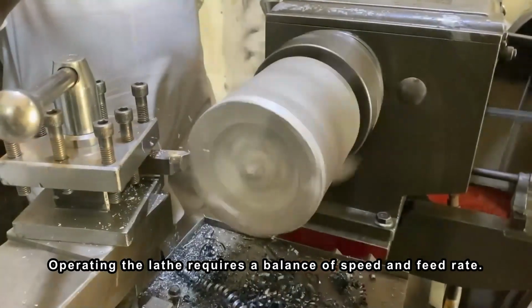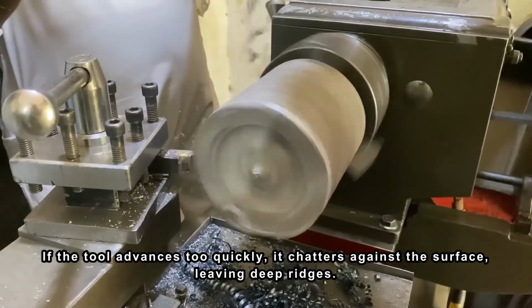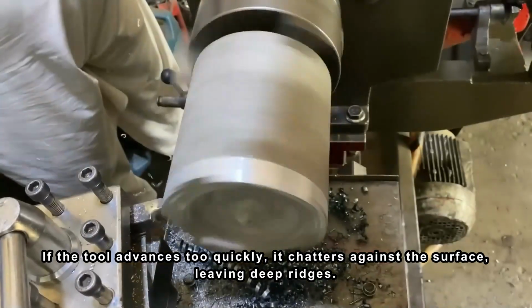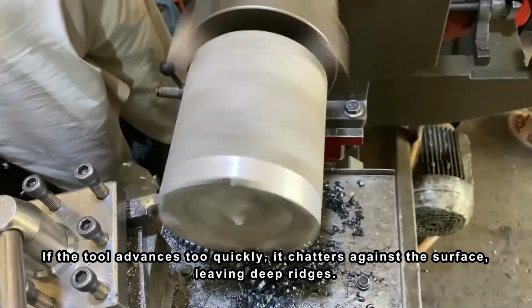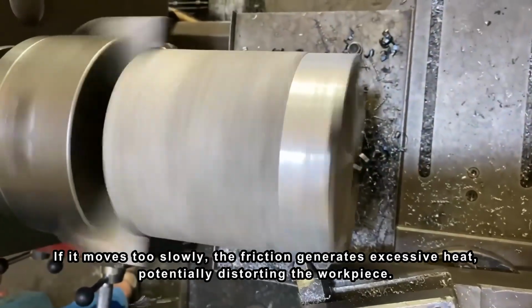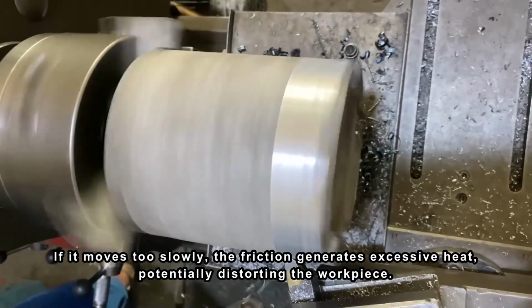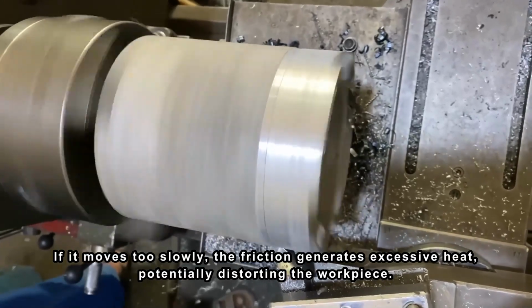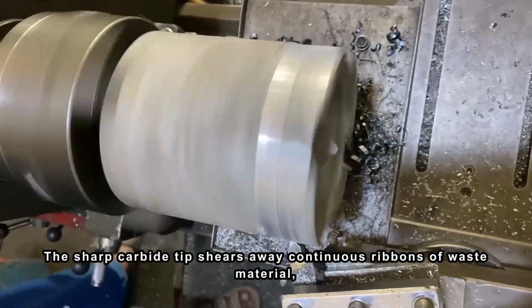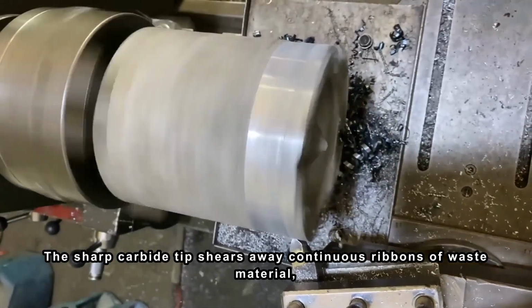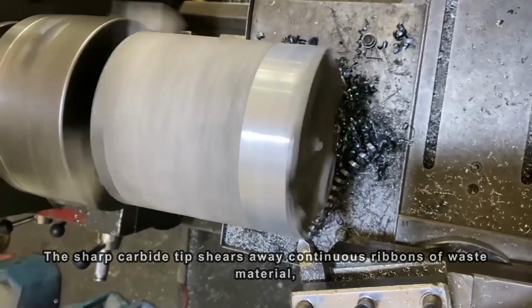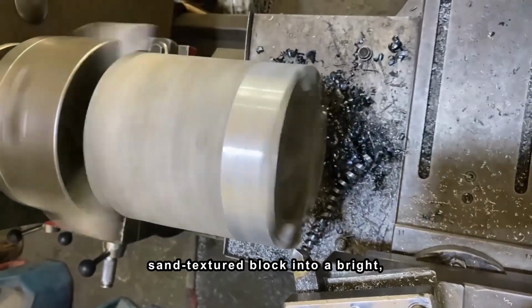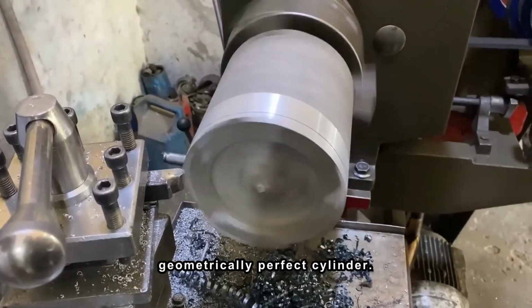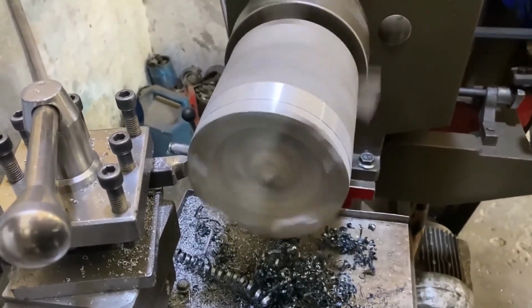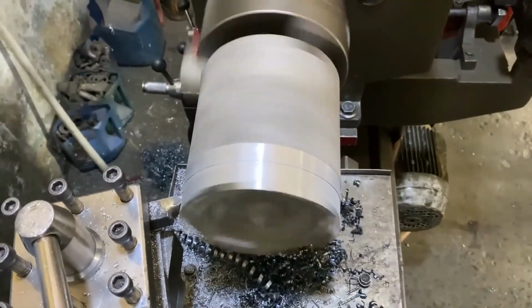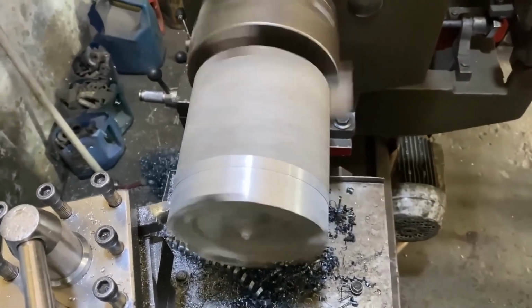Operating the lathe requires a balance of speed and feed rate. If the tool advances too quickly, it chatters against the surface, leaving deep ridges. If it moves too slowly, the friction generates excessive heat, potentially distorting the workpiece. The sharp carbide tip shears away continuous ribbons of waste material, transforming a coarse, sand-textured block into a bright, geometrically perfect cylinder.